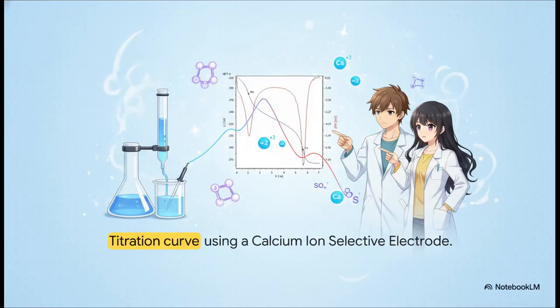Once prepped, we titrate. Take a look at this titration curve using a calcium ion selective electrode. It's a total chemical balancing act. A titrant is slowly added and the electrode tracks the voltage. You see those sharp, sudden dips in the red line? Those are our equivalence points. By tracking that massive voltage drop, the system knows exactly how much titrant was needed to react with all the sulfates. The precision is just staggering.